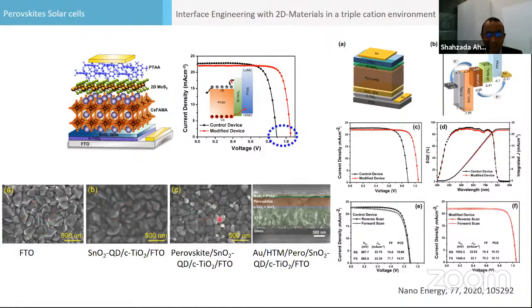This is the crystal of the perovskite. This is the cross-sectional diagram of devices. We cannot see the MoS2 layer because it was buried under the PTAA, a hole transport material. But the devices have very high performance, and they work very well. The control devices give you only 15%, but these devices work very effectively and give us 18%, 19% efficiency, and much more stable devices we have observed.